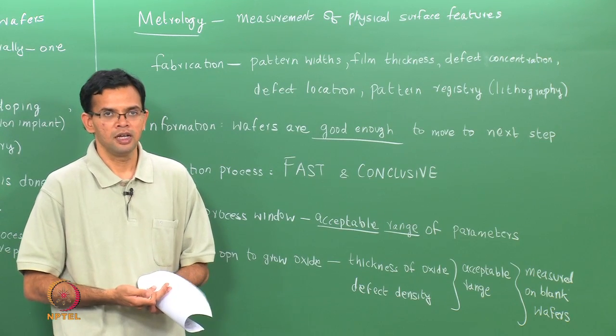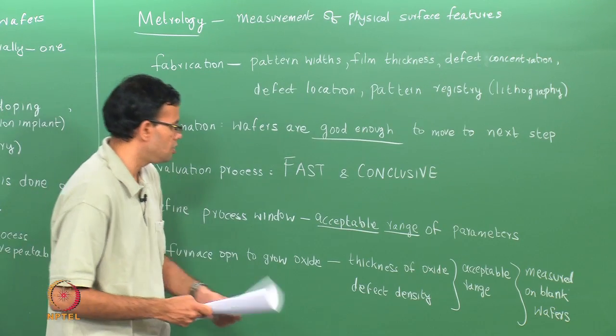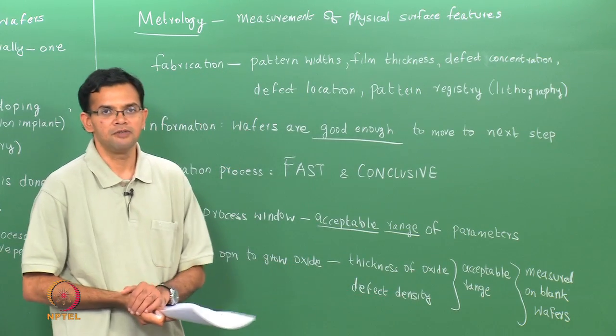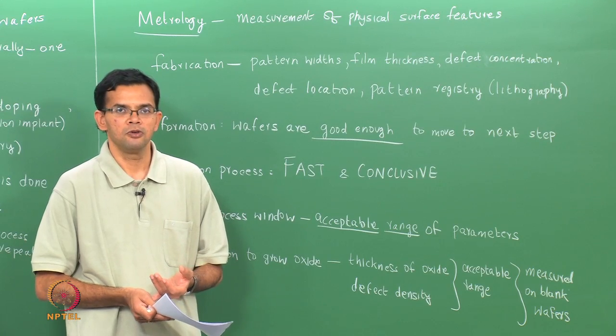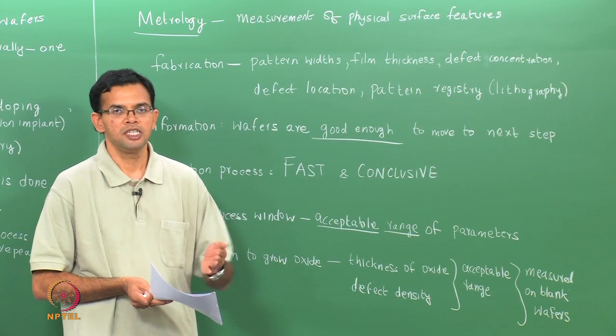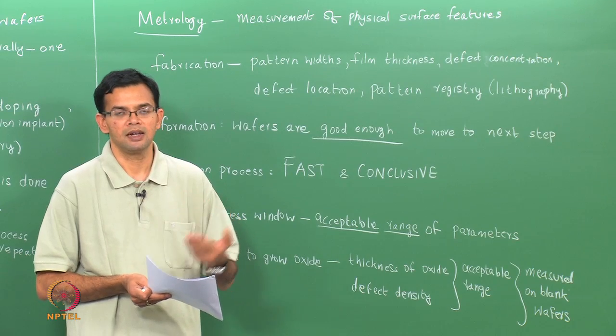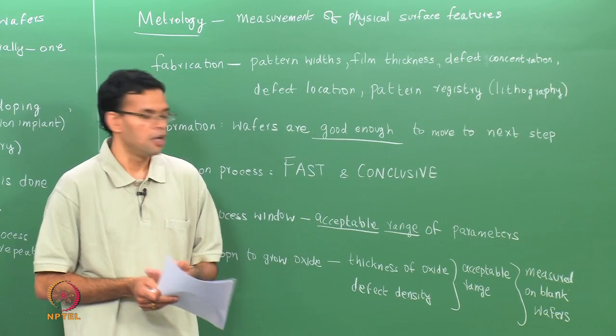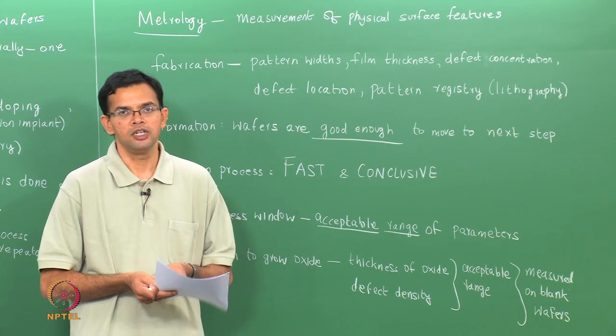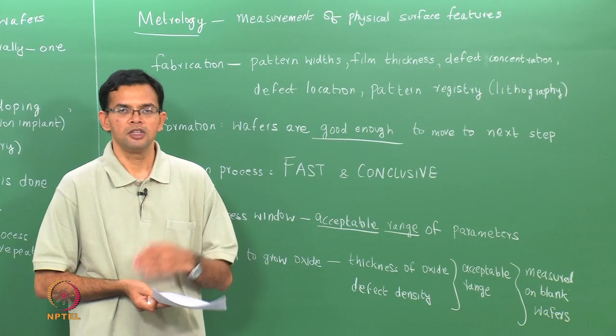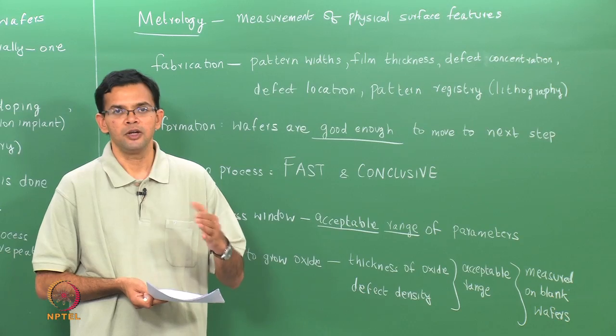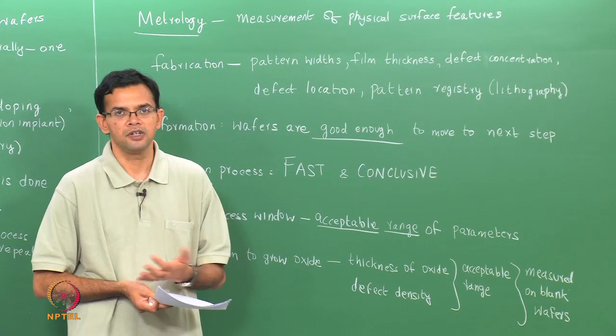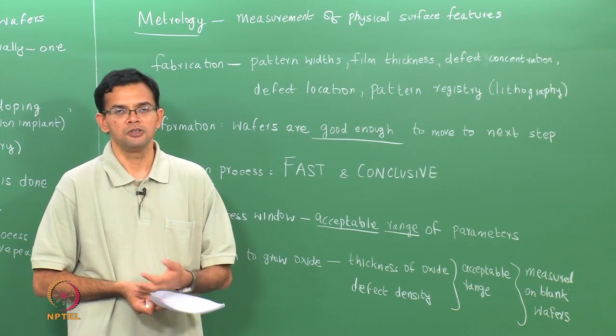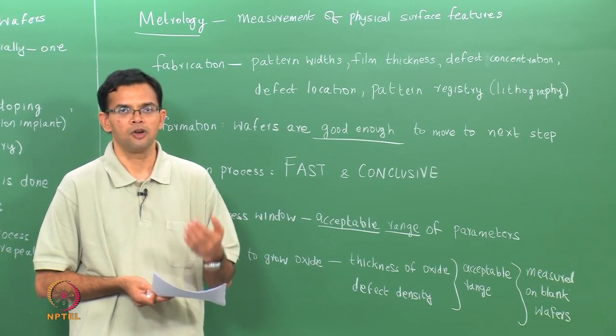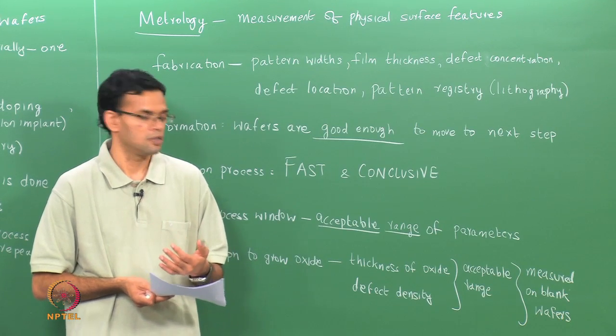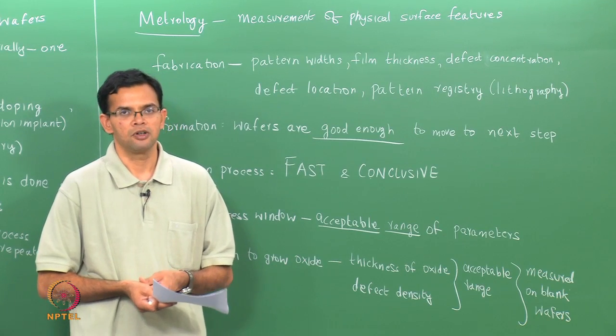The drawback, of course, is if there is a problem with the process which causes either a thickness shift or a high defect density, because it is a batch process, you will essentially affect more than one wafer, which means if the wafers have to be scrapped, when we say scrap, those wafers are condemned and destroyed. You will not only destroy one product wafer, but you will destroy multiple product wafers. So, if you think about a furnace operation with say 125 wafers, typically 100 wafers are product, so that if the furnace operation goes bad, we would essentially scrap 100 product wafers, which will again lead to increased cost. So, that is the one drawback if you have a batch process.